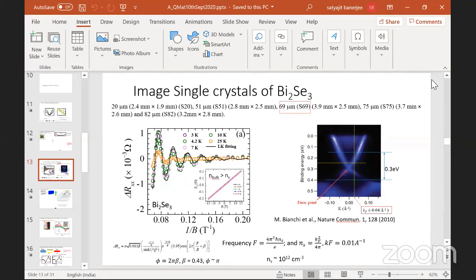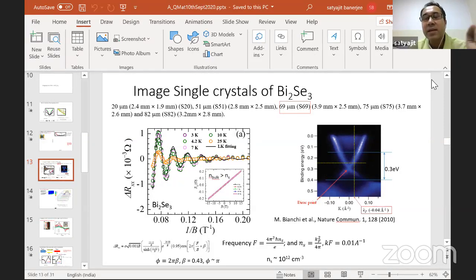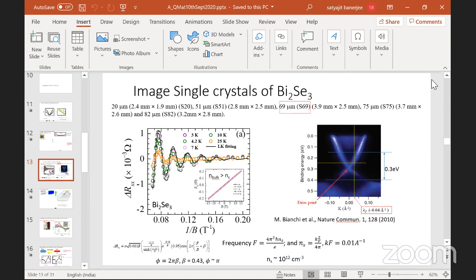Okay, so Dr. Tirupataya Sethi, you may ask. It's more or less similar to what Gautam Sheth asked. Did you cross-check with a system without conduction band contributing to your resistivity? There are certain systems where there is no conduction band below the Fermi level, where they tune the Fermi level such that this conduction band is absent. You mean systems where you have actually made the bulk absolutely insulating? Yes, exactly. Did you cross-check? So that is something that we are currently doing. There are certain good single crystals we have managed to get from some collaborators abroad, and they have supplied us the crystals. We are doing that on those crystals.